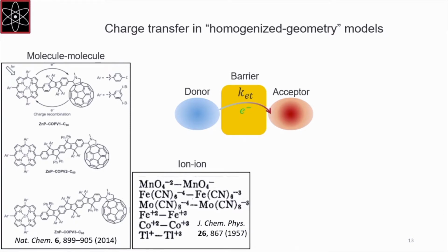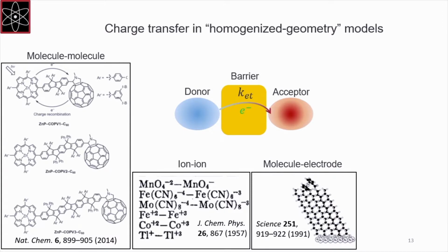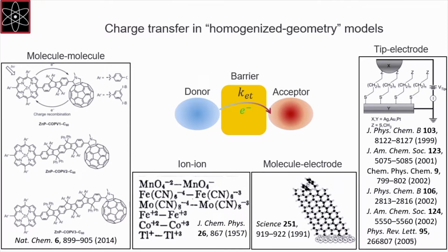And people also have tethered donor-acceptor pairs using a rigid organic molecule, and by varying the number of repeating units, systematically increasing this parameter, the distance between the two, basically the width of the barrier. And one can also study the transfer process between electrodes and a molecule, but also using a very controlled self-assembled monolayer to precisely control that distance. And of course, in the scanning probe community, using atomic force feedback or tunneling feedback, one can also very nicely control that distance to achieve what I'm calling here homogenized geometry.